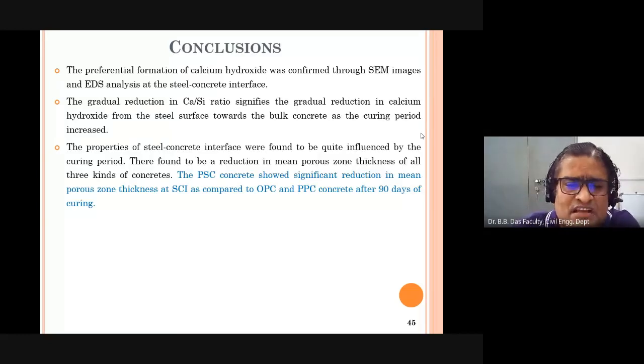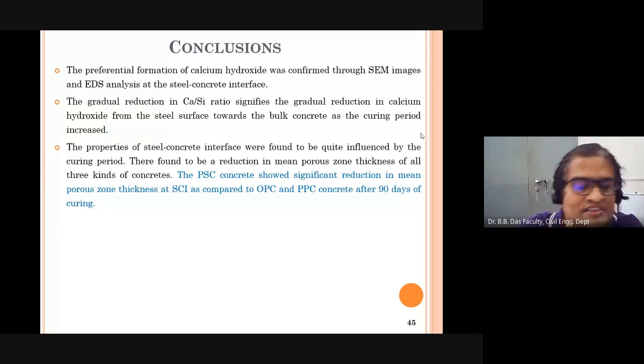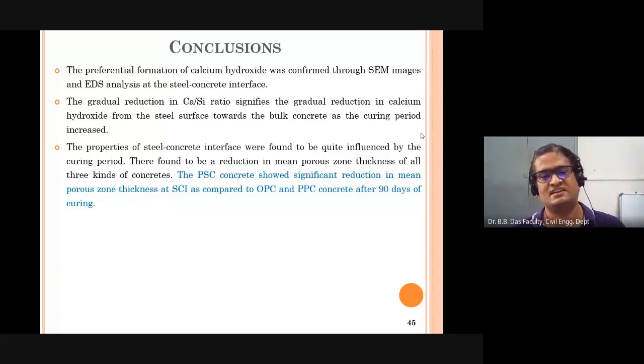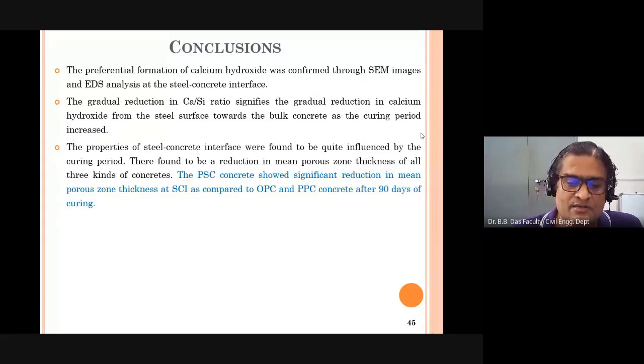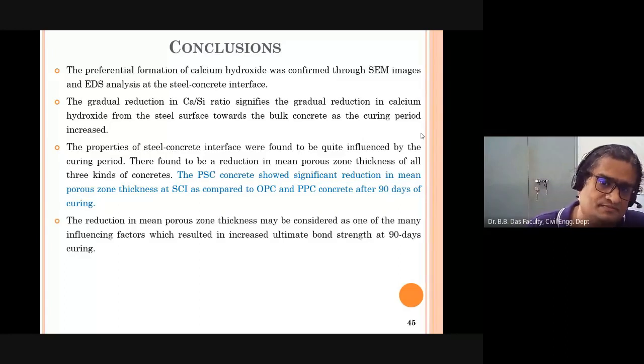Then the properties of the steel-concrete interface were found to be quite influenced by the curing period. There was a reduction in mean porous zone thickness of all three kinds of concrete from 28 days to 90 days. The PSC concrete showed significant reduction in mean porous zone thickness at the steel concrete interface as compared to OPC and PPC concrete at 90 days of curing. I was telling you that Portland slag cement shows better performance as compared to both the other types of cements.